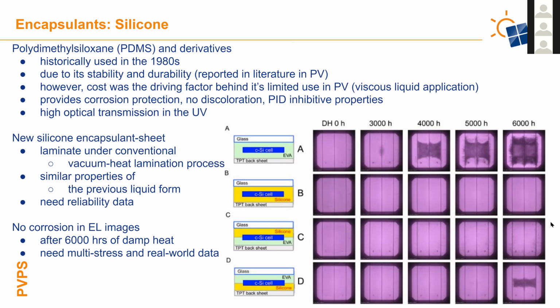In this figure, the top line is EVA as the encapsulant front and back. B is silicone front and back, and C and D are different front or backside silicon. With just EVA, we still get this corrosion, this acetic acid formation, and it causes corrosion in our cells. You also see it when EVA is on the top, but not necessarily when EVA was on the backside. So this is an opportunity potentially to have different types of encapsulants together, and you may be able to lower the cost by using EVA, but potentially on the backside. There's still more research needed in this area.